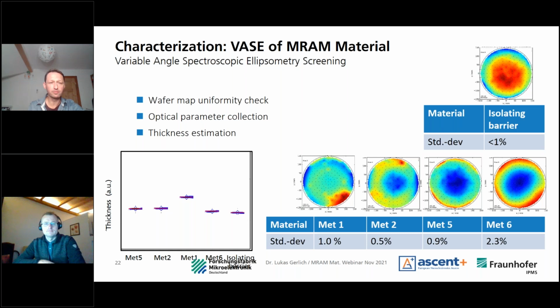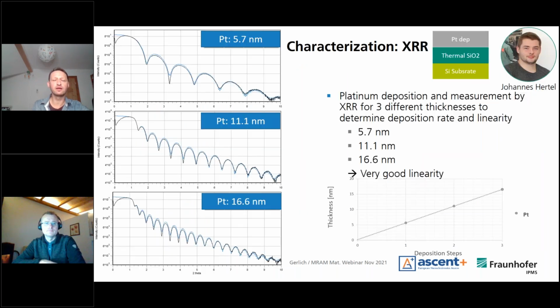We have here used a variable angle spectroscopic ellipsometry screening. This is suitable not only for uniformity check, but also to obtain better optical parameters out of each material, and then to have a thickness estimation. Here are 5 typical materials, as I told before, and the non-uniformity is mostly superior and can be cross-checked by X-ray reflectometry, which is for sure not that model dependent like ellipsometry.